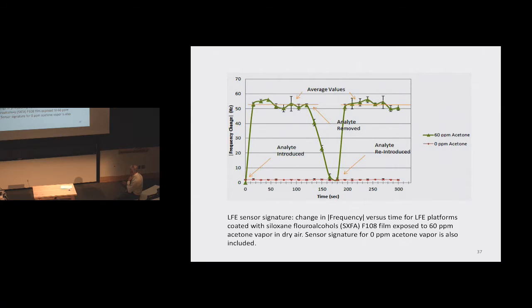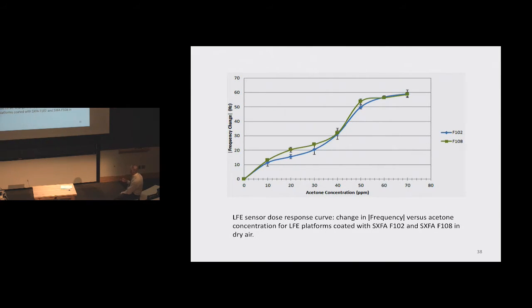And the film is given over here. It's the siloxane fluoroalcohol. And this represents even more data associated with that polymer film. This was done in dry air. That's for acetone. We looked at a couple combinations of films. These are 2 different films, prepared with a very similar base and different types of additions here. And this is, again, detailed in publications that we have, the blue one representing one and the dark one representing another.